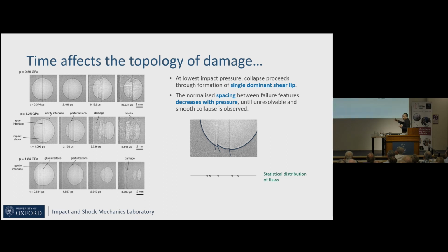So we can do that experiment a few times. We can run it at a variety of different velocities because, again, we're trying to change the amount of energy we put in. We want to see where the energy is going. And so we can do it at low velocities, medium velocities, and a little bit higher velocities in the strength regime. And I guess the key takeaway here is maybe you can see evidence of a little shear lip here, and you can see possibly more perturbations. I've put a label there. And as we increase the velocity, the spacing between those perturbations decreases. To help you understand this, I've drawn where those shear lips are in this frame here.